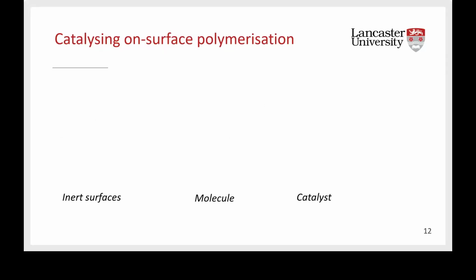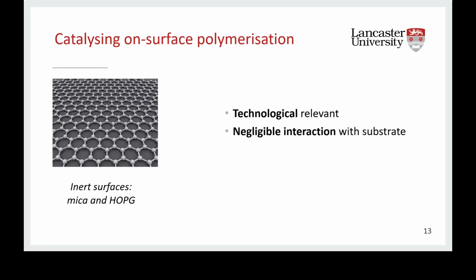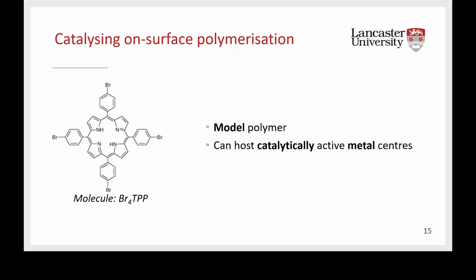We have an inert surface, so a surface that's just confining the monomer into two dimensions, a molecule, and a catalyst. As inert surfaces, I use mica, which is an atomically flat insulator, and HOPG, which is a zero band gap semiconductor, because that's technologically relevant. Second, we need a molecule. And I'm actually using the molecule I showed you before, called the bromophenyl porphyrin. This is a model monomer because it has 4 carbon-bromine bonds. I can thus form a two-dimensional square lattice. And porphyrin can host in the middle metal atoms that are catalytically active.